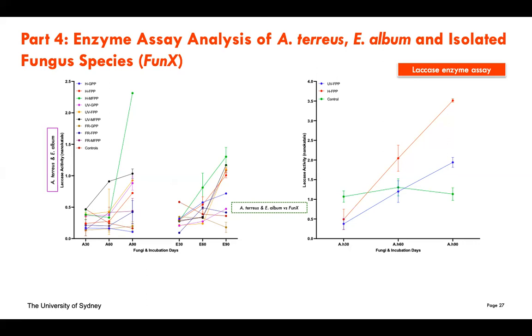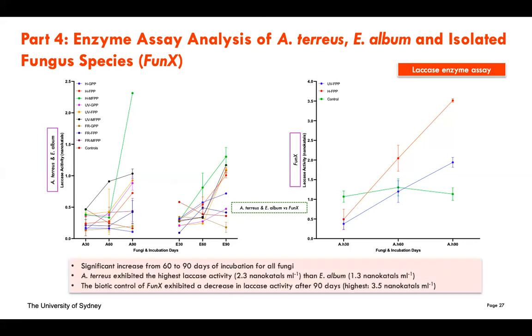So this part shows the laccase production. If you look between the left, the A. terreus and E. album, and the right, the new fungal isolate, you can see that the amount of laccase produced after 90 days is much higher compared to the A. terreus and E. album. The new isolate produced about 3.5 nanokatals, which is a unit for the enzyme. But for the previous fungi, the Aspergillus teres produced the highest, about 2.4 nanokatals. So the new isolate produced a much higher laccase.